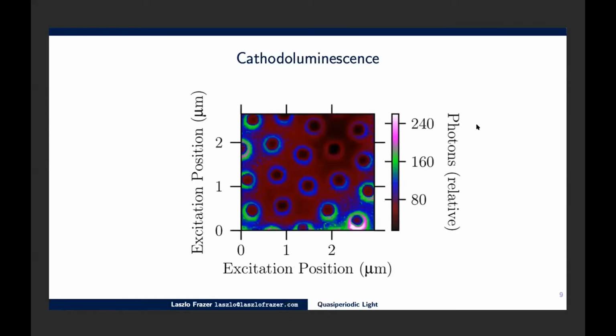This is a cathodoluminescence image. This is a really different kind of imaging mode. So the near-field microscopy sees where the light's coming out. The cathodoluminescence sends in a beam of electrons and then detects light from everywhere. So what we're measuring here is what's the position where when you inject an electron, you get a photon out. So this is sort of more like, where does the energy come from rather than where does it get converted into light?